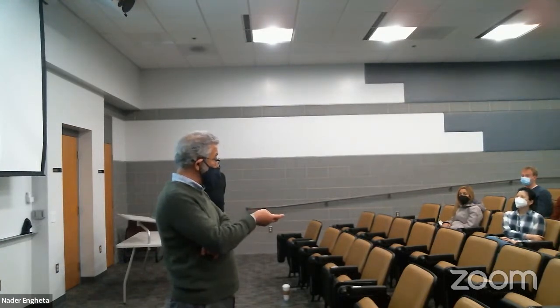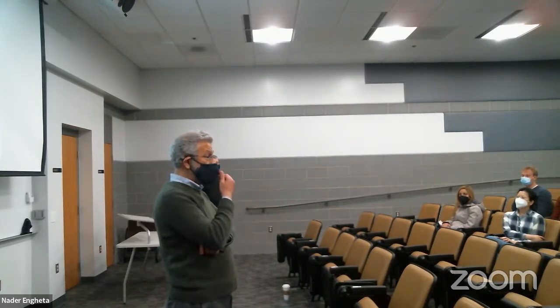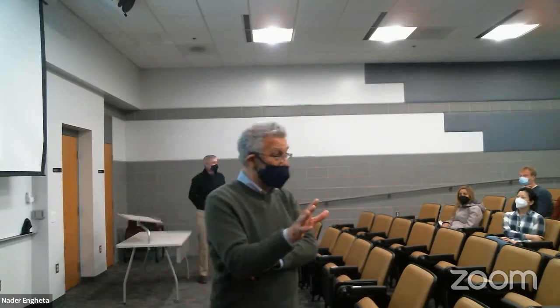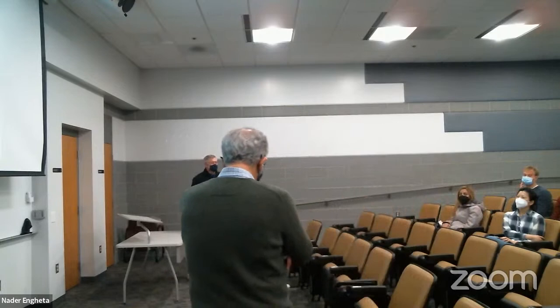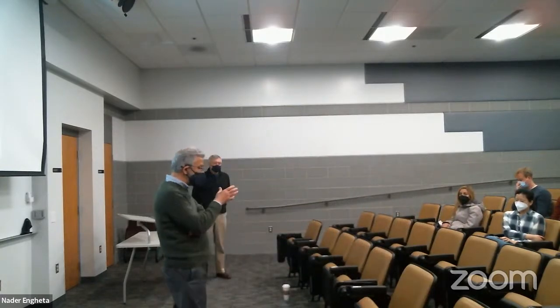But one thing we have to be very careful about, and thanks again for your question, Bill, is that even though we call this near zero index, there are actually three categories of near zero index material. One is when epsilon is near zero, but mu is not. The other is when mu is near zero, but epsilon is not. The third is when both are near zero. Taking the dispersion into account, these three have different dispersion properties. We recently studied how the dispersion of these three different structures, all being near zero index, will affect this. Some of those can have an interesting effect on the momentum aspect that you asked about.